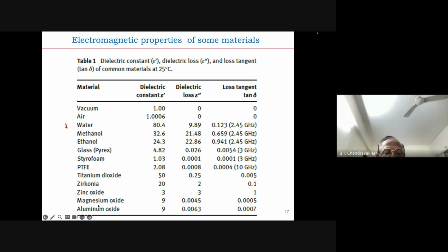Look at the last row, aluminum oxide, which is a workhorse of ceramic materials. The epsilon double prime, which is a dielectric loss constant, is very low, 0.0063. And therefore we say that aluminum oxide doesn't absorb microwave easily. So is the case with magnesium oxide. They are all transparent to microwave. But this is only at room temperature. As the temperature increases, we will see that part later, the epsilon double prime increases. Therefore, at higher elevated temperatures, it will start interacting with the microwave.